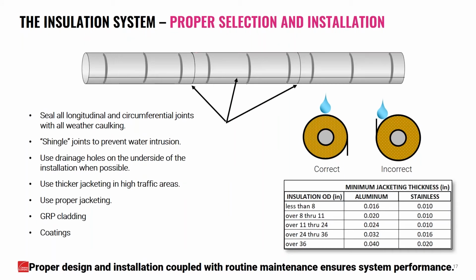Now, that's the insulation part of this. The other part of this, we talked about earlier: you want to make sure you properly select and install the insulation material and the insulation system. You always want to make sure that you're sealing along longitudinal and circumferential joints. You want to shingle joints like we talked about earlier, and there's an example of this over on the right-hand side. If you see between the correct and incorrect, if that water drop falls on top, it's going to shed off that lip. Whereas if you look at the image on the right, you can see that water droplet is going to go right into the jacketing and then right into the insulation system.